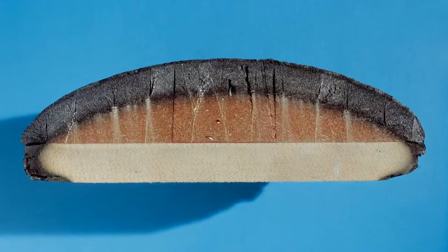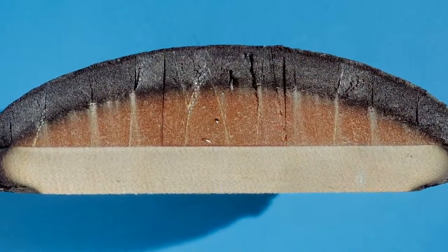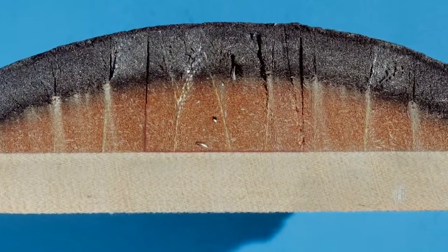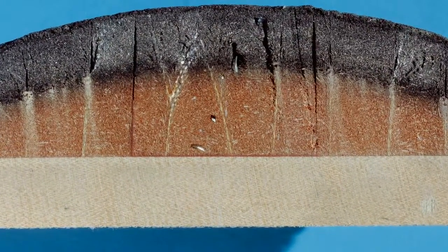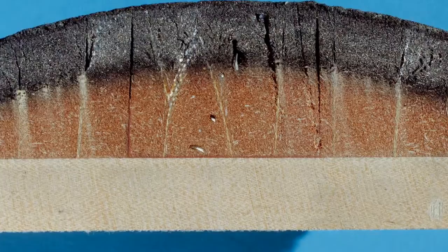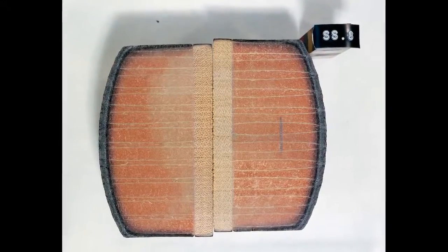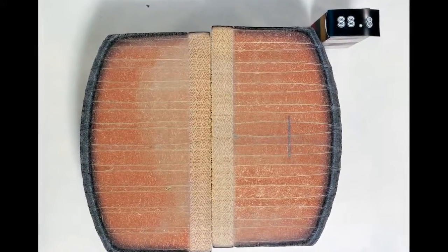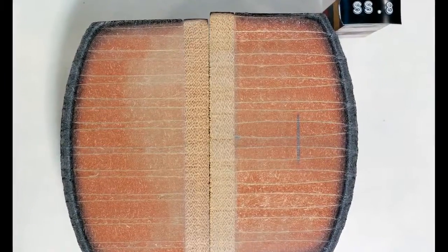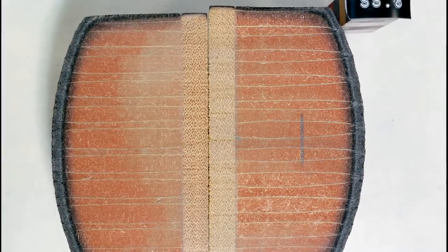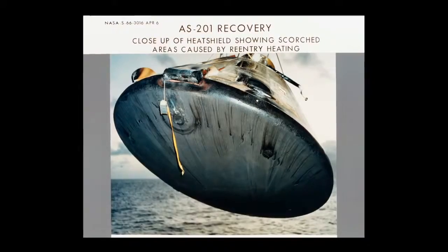However, we took the ingredient out of the material, retested it, and it was much better. So the facility allows you to test those things and make judgments on the material itself. Absolutely. The Apollo material, because of the ArcJet testing, went from a high density material of around 60 pounds per cubic foot all the way down to around 32 pounds per cubic foot by the addition of some fillers, we call them, within the material. And we still got really good performance.